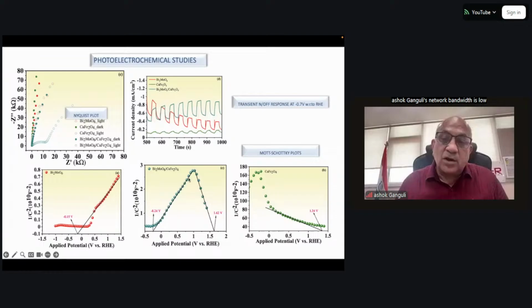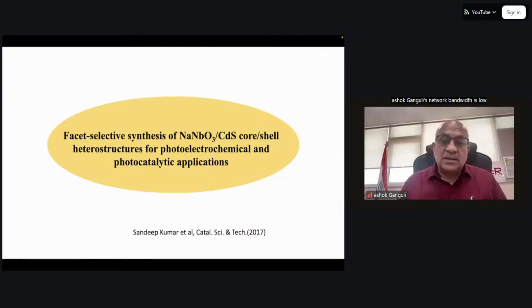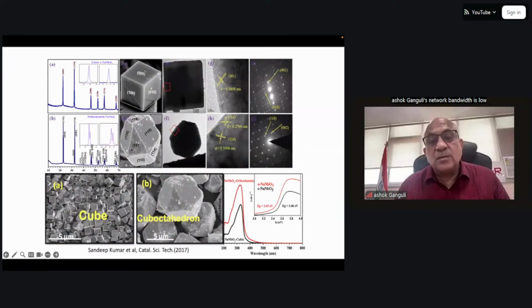This is again a Mott-Schottky plot showing you both N-type and P-type charge carriers, which is like what I discussed earlier. This is another idea: if you can have different facets, you are making a core-shell kind of structure like earlier, but now can you control the facets and show enhancement in the efficiency of the photoelectrochemical process. So here we did prepare two types of morphologies, a cubic morphology and a cuboctahedral morphology of the sodium niobate, which is at the core, and the other semiconductor you then put on top of this.